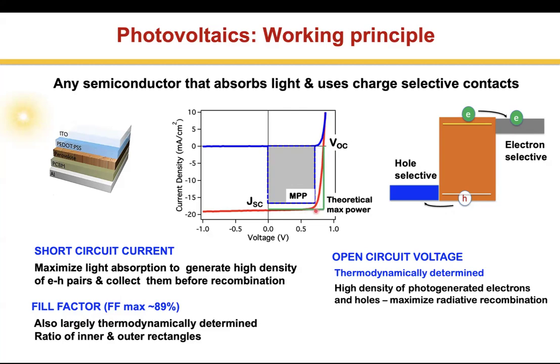And it also comes from thermodynamics, because you're now losing some voltage to do this. It is really the ratio of your actual max power to what maximum you can get, which is basically determined by your maximum short circuit current and VOC. And so the best you can do is like 89%.